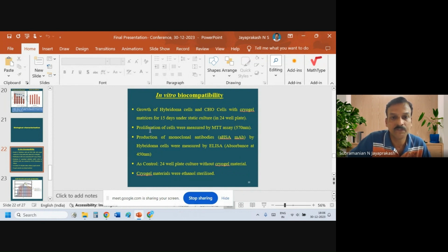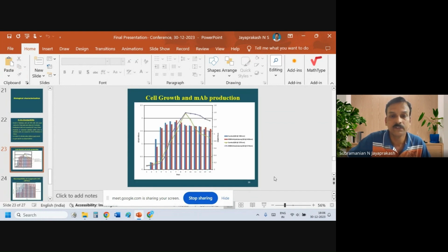Here, the proliferation of cells was measured by MTT assay at 570 nanometers, and production of monoclonal antibodies by hybridoma cells was measured by indirect ELISA method, that is absorbance at 450 nanometer. As a control, we had 24 well plate culture without this cryogel material. And all the cryogel materials which were used in this study were ethanol sterilized. So this is the result which we got in the biocompatibility study.